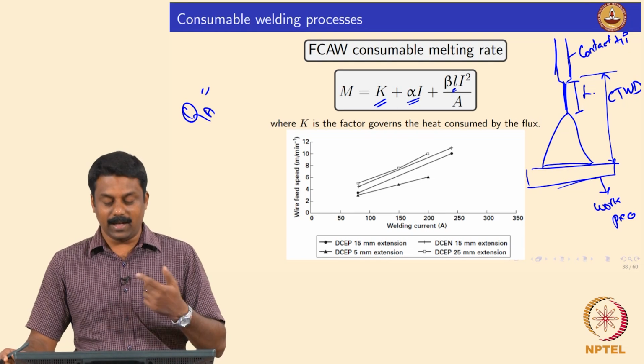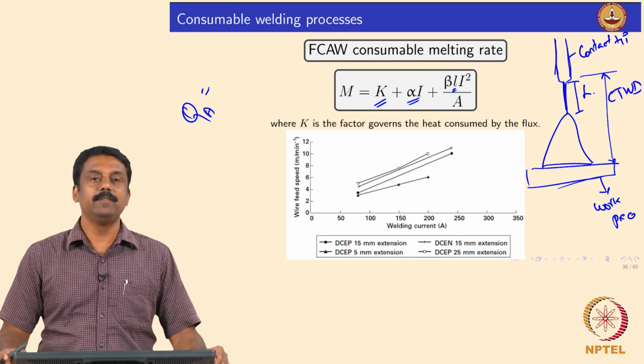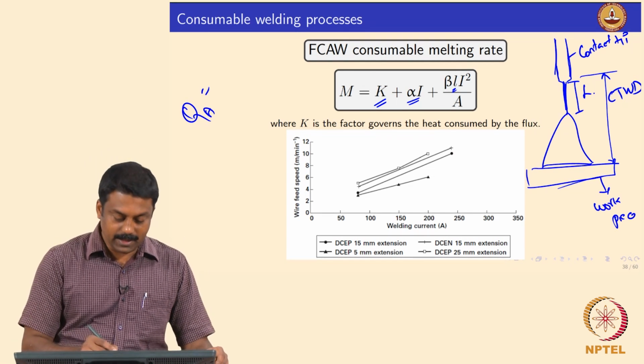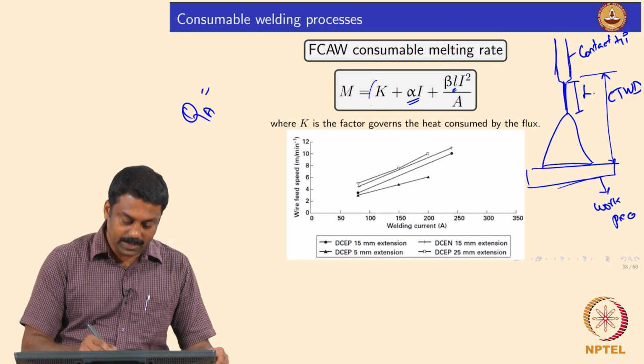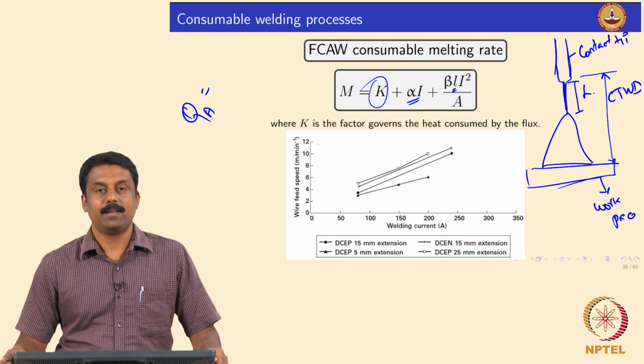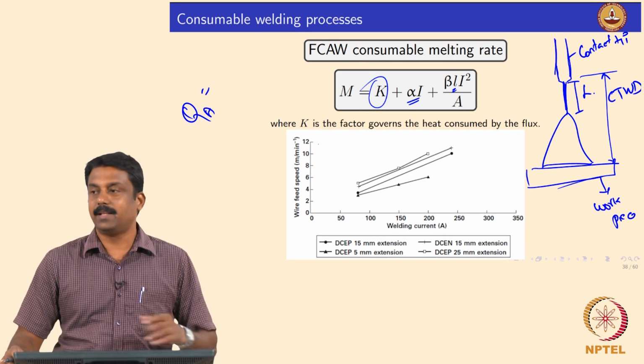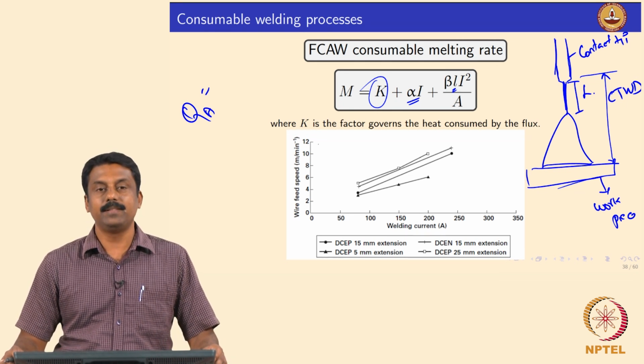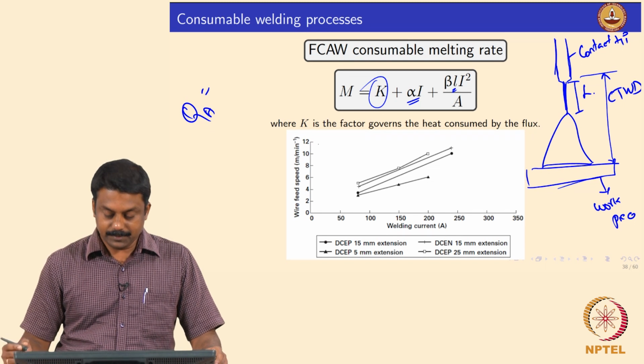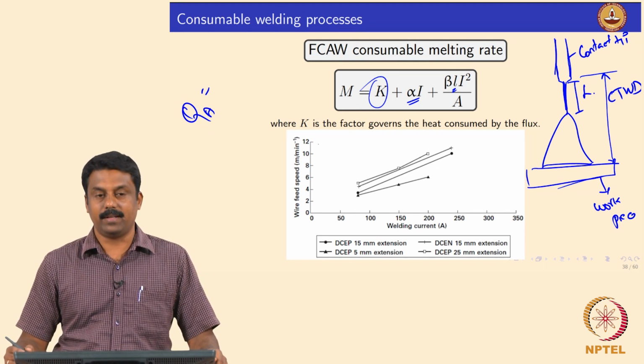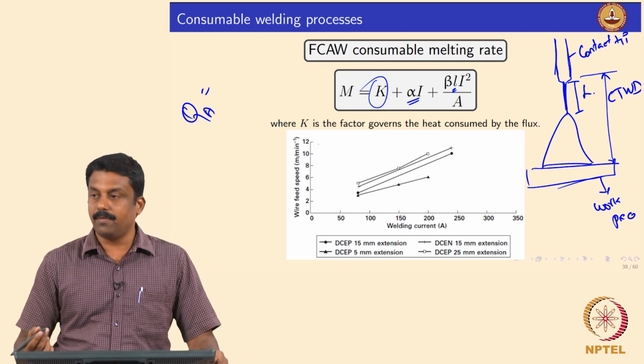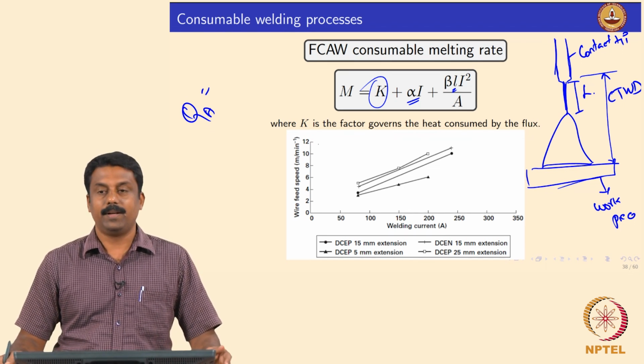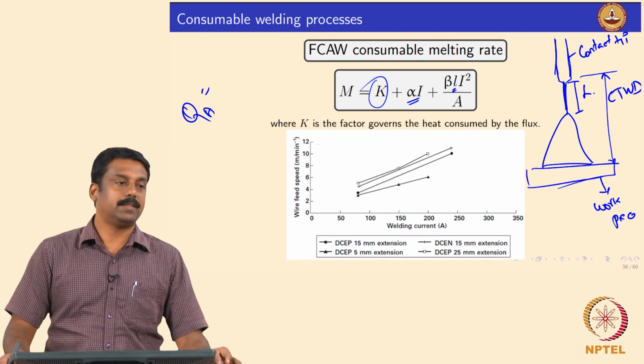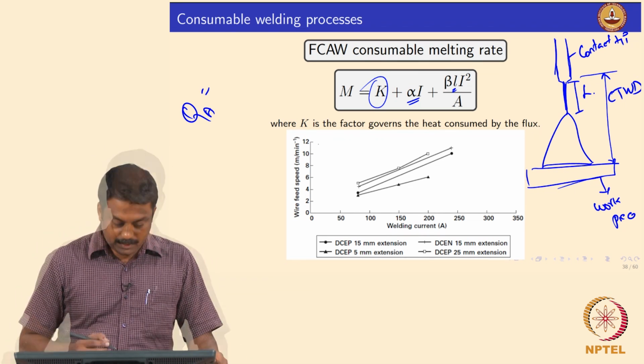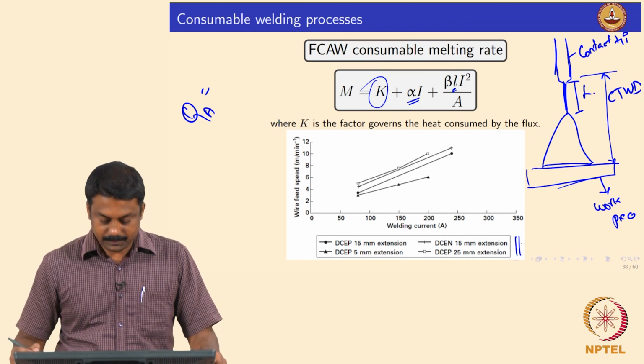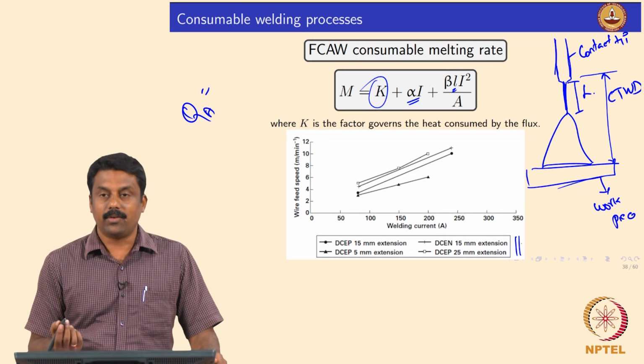Apart from these 4, there is another factor when you use consumable welding. Which factor is that? Heat absorbed or eaten away by the flux, right. So, there is another component that comes in when you are doing a mass balance or heat balance, the K factor. That factor governs the heat consumed by the flux. Again, that is a function of the composition of the flux, whether you have a rutile based or a basic flux or cellulosic material. So, again as a function of stick out length, we can also calculate the wire feed rate.